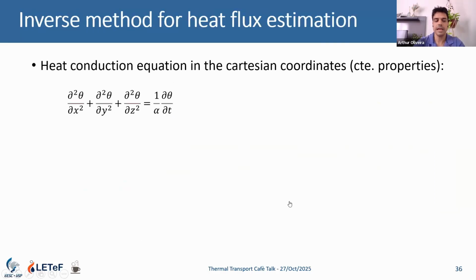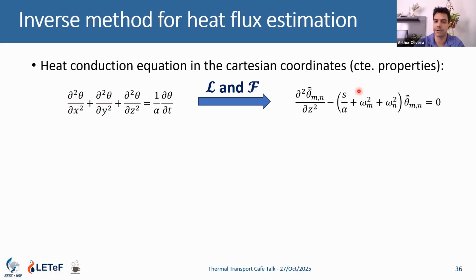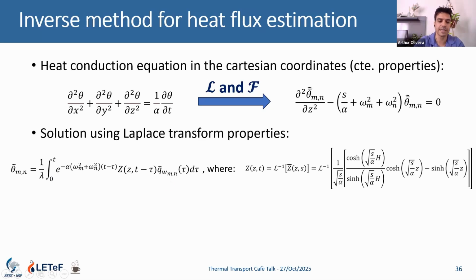So as before, we need to develop an inverse method here to quantify the heat flux field over time for our droplet impact process. Now we have a 3D transient problem, and we use Laplace and Fourier transform to get an ordinary differential equation. Using Laplace transform, you have the solution in the Laplace space. We also use an algorithm, the same algorithm, to invert the Laplace function.